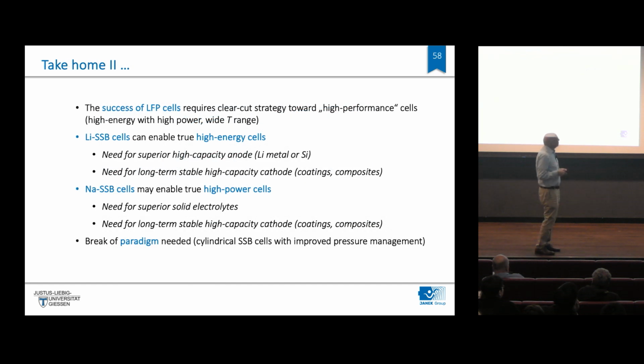Okay, now, the take-home message at this point is simply that lithium-ion batteries are moving targets. They get better and better and better, but they will not exceed 400 watt-hours per kilogram. You can only overcome that with lithium metal anodes, but their safe operation is today not secured. I would say it's a big bet whether that will operate. We still have fundamental issues to be solved, by really tackling the metallurgy of lithium metal and sodium metal properly. Then we can have true high energy cells. I'm pretty sure we can also have high power cells if that is solved.